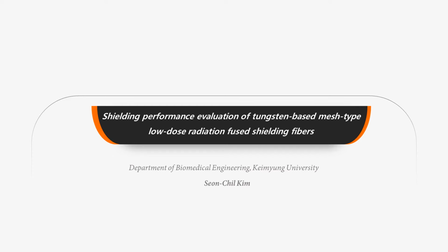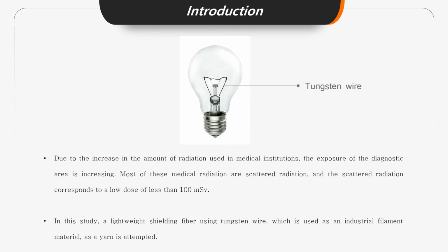This study is a study on the radiation shielding performance of shielding fibers woven using industrial tungsten wire. Due to the recent increase in the amount of medical radiation used by medical institutions, radiation exposure in the diagnostic area is increasing. Most of the radiation that is a problem in medical institutions is caused by indirect radiation rather than direct radiation and generally means scattered radiation. Scattered radiation corresponds to a low dose and means a dose of less than 100 millisievert of low-dose radiation.